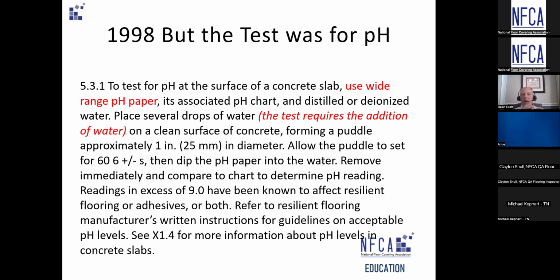So a lot of manufacturers just package them together. But what I want to point out is that pH cannot be measured on a dry surface. So you can't take a pH strip and just touch it to the concrete surface and get a reading. You need a solution. So to even measure pH, you had to add water. You had to wait, and then you test the pH of the water. So you're not actually testing the pH of the surface of the concrete. You're actually testing the pH of the water that was placed on the concrete.